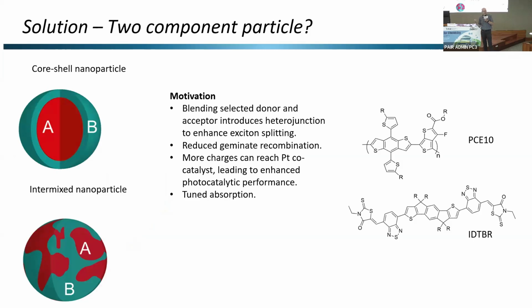So what we thought was, so my background at this point was in organic solar cells. And organic solar cells have solved this problem already. So what they do in an organic solar cell in order to generate free charges is to create an internal heterojunction. So an offset in energy level between two components that allows a thermodynamically favorable charge transfer process, either an electron transfer or a hole transfer, in order to create free charges. And that's how solar cells work. And you sweep these charges due to an internal field. In a nanoparticle, of course, we don't have an internal field. So we require drift of our free charges to get to the co-catalyst, usually platinum, on the surface.